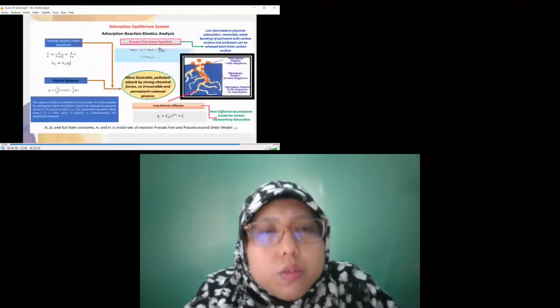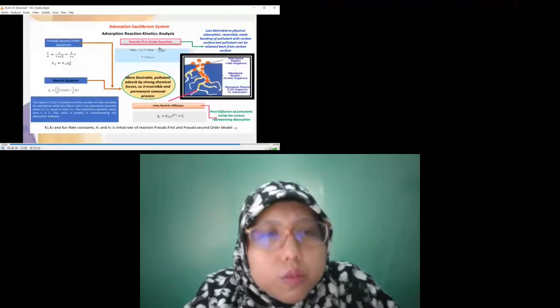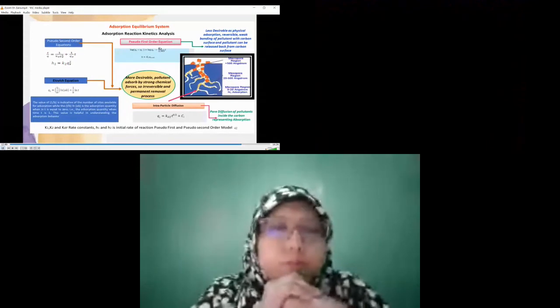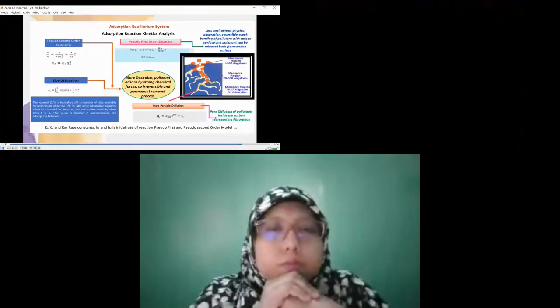This is the pseudo first order reaction equation, and there is an equation constant K1. Then pseudo second order reaction. Pseudo first order is less desirable as it happens for physical adsorption. Pseudo second order is more desirable because it shows chemical adsorption, which is irreversible. Intraparticle diffusion is checked to see whether the adsorption process is taking place, that means whether any pollutant has gone inside the core or not.